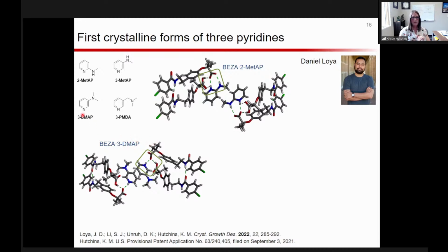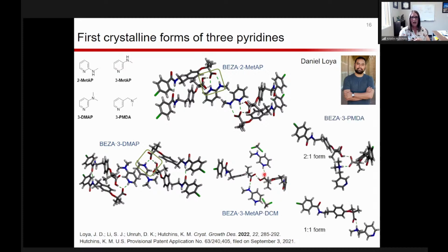And the structure with 3-DMAP, this one here, is essentially almost isostructural, with very similar behavior of the acid groups. In the case of the 3-methylamino-pyridine, we actually got dichloromethane present in the crystal lattice as well, adjacent to these main interactions. And then we had a really interesting case, where mechanochemistry helped us get 2 forms with 3-PMDA. We isolated a 2-to-1 form, so you can see 2 of the drugs here and then 1 of the pyridines. And we isolated a 1-to-1 form.